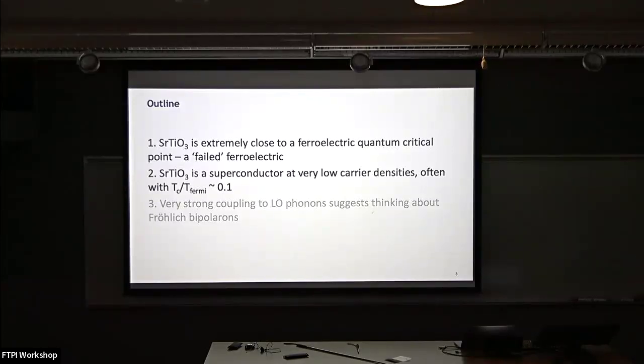Possibly related, but not necessarily related. There's another reason strontium titanate is interesting: it's actually a superconductor, at extremely low temperatures. However, it's a low TC superconductor, even though TC never gets to 1 Kelvin. You're in a regime where the Fermi temperature is 10 Kelvin, and all of the relevant modes that it is coupling to are bigger than the Fermi temperature. So why it is doing that has also provoked a lot of interest.